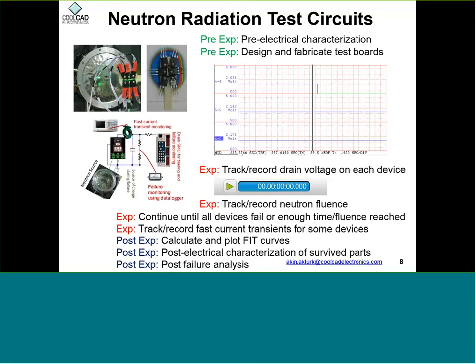Then we put our devices in the path of these neutrons, and the biggest collimated output of this source is about 3 inches in diameter, and you can fit up to 6 devices within 3 inches. You can also stack them back to back, but as you stack more of them, you lose some of the neutron spectrum because of the scattering by the first and the consecutive stages. So it is better to put one set of devices within the direct range of these neutrons. Next to this beam output, you can see how uniform the beam output is, specified by that blue area, and how 6 devices can fit into this irradiated area.